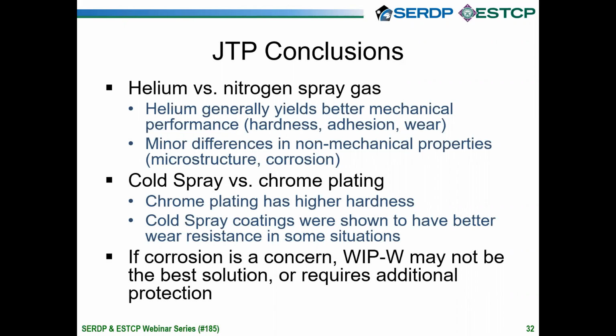The second observation, when we compare cold spray to chrome plating, we found that chrome plating has higher hardness than our cold spray coatings, but our coatings were shown to have better wear resistance in many different loading situations. Finally, for corrosion, we found that WIP-W may not be the best solution for corrosion protection, or it requires additional protection.